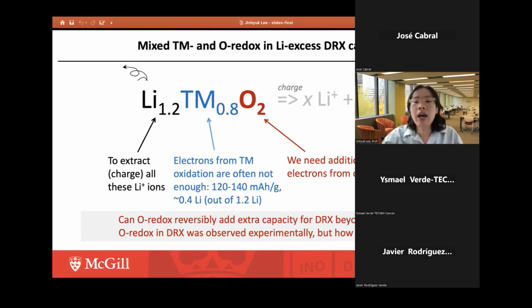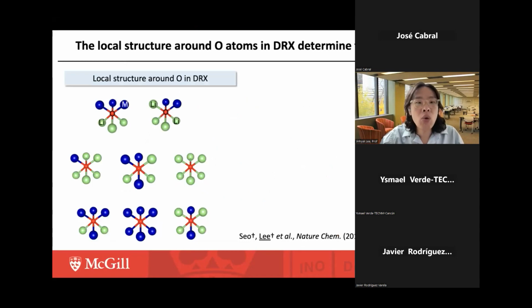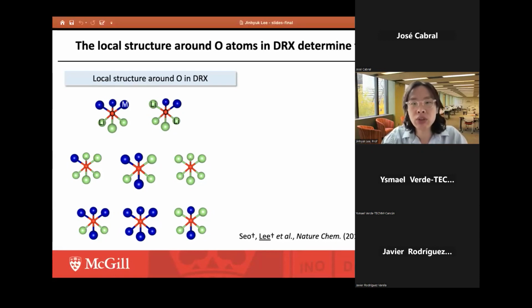But now the question is, how does this mixed oxidation of the transition metal and oxygen occur during charging and discharging, right? So to understand this fundamental question, we performed a theoretical study, and in particular, we tried to study the effect of the local structure around oxygen atoms in the DRX structure on the oxygen redox activity.